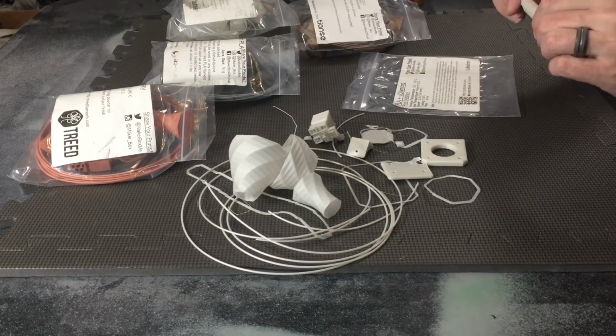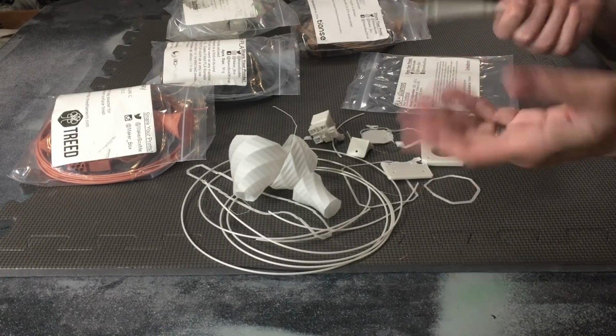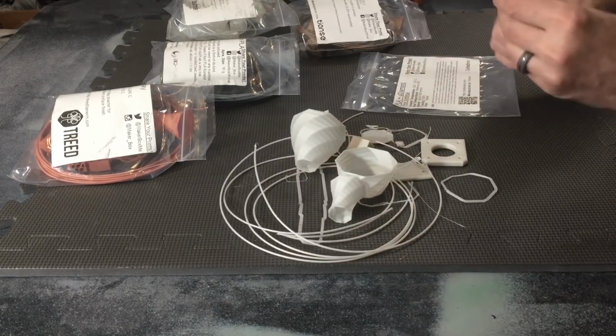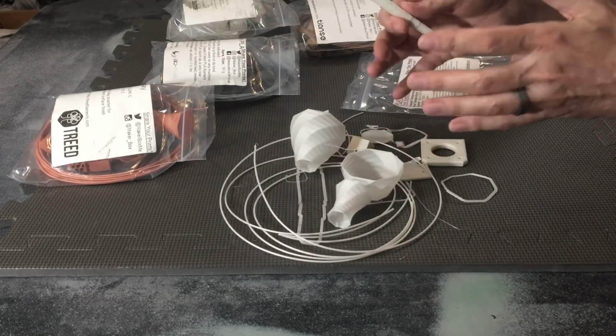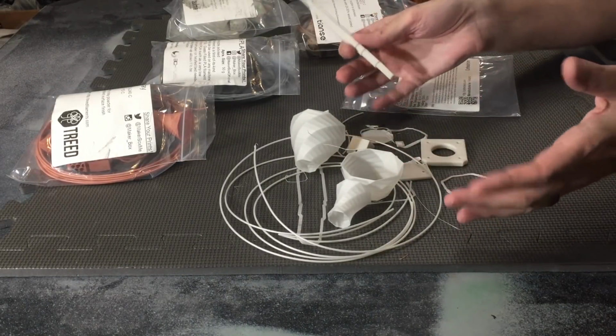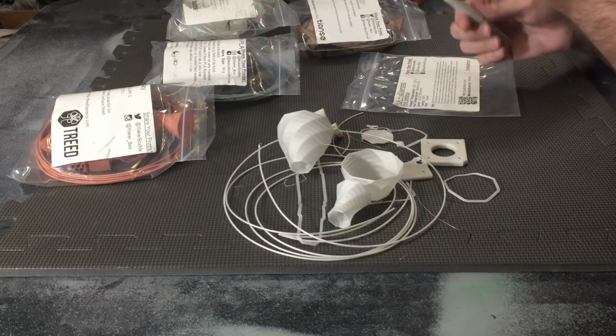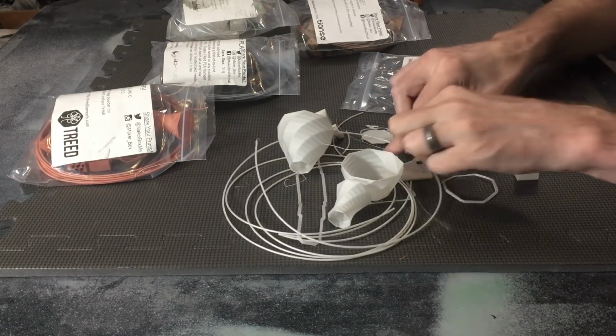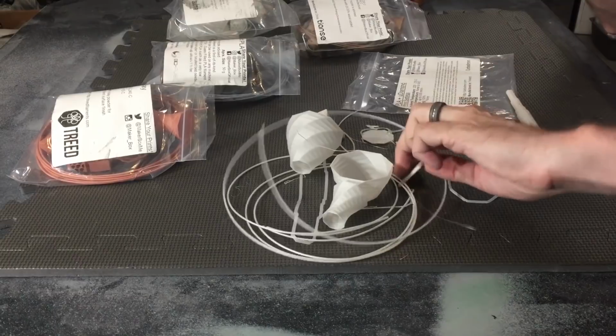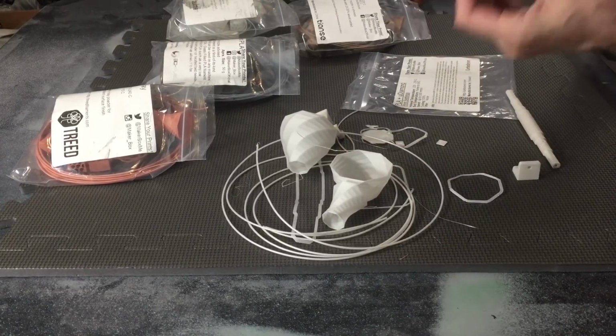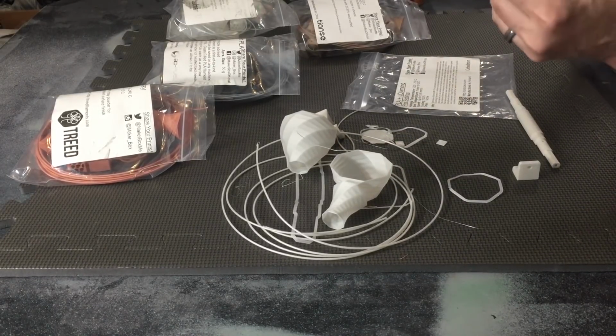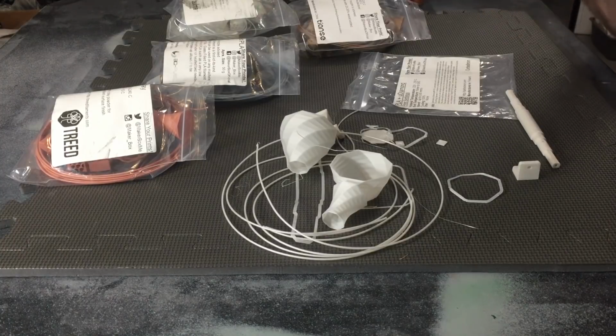Overall, I think it's a strong filament, but I can't tell. I need more of it, obviously. 50 grams isn't enough. It's very cool to test with this type of filament, and this is enough for me to do this much testing to see that it could possibly be a strong filament, but I don't like that dropping it down to 220, which is like a high-end temperature for PLA anyway, gave me terrible layer adhesion.